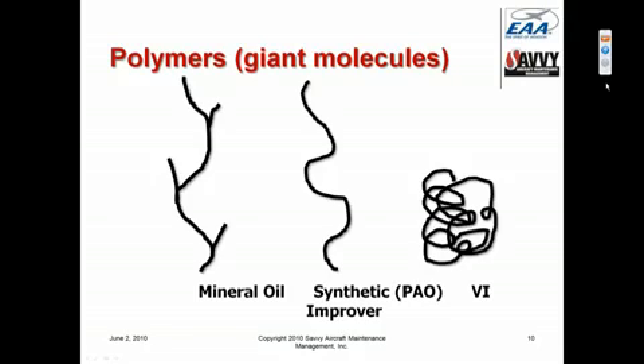Now, the shape of the mineral oil molecules and the PAO molecules is fairly significant. They explain a lot of the properties. Synthetic oil is slipperier because it doesn't have the side branches. Mineral oil, because it has the side branches, has two properties that synthetic oil doesn't have. One that's a positive, one that's a negative. The negative is that mineral oil, as it operates in service, has viscosity that gradually degrades because the little branches break off when the oil is in service as a lubricant between rapidly moving metal surfaces. So the longer you keep mineral oil in service, the more its viscosity degrades.